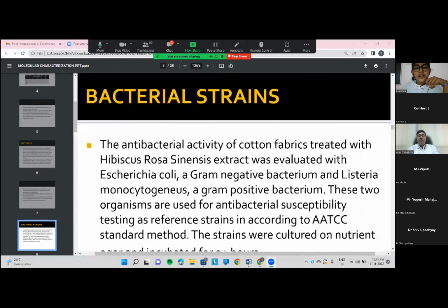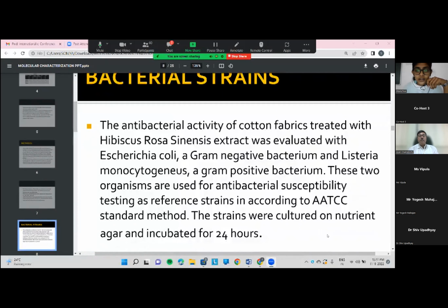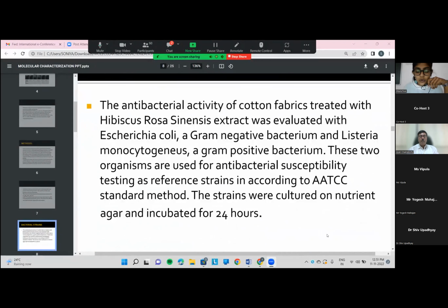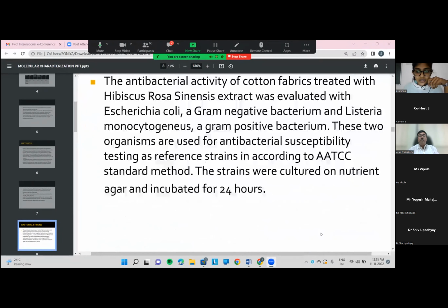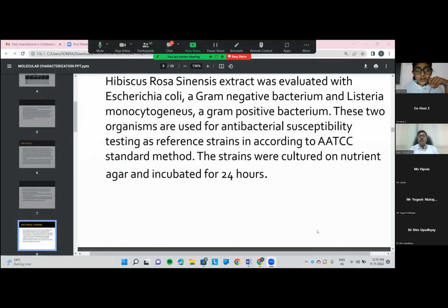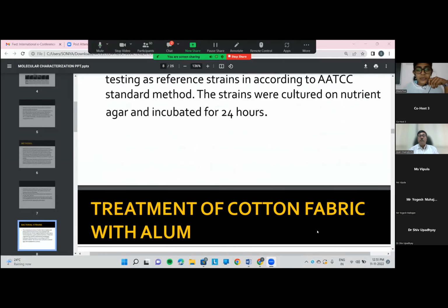Bacterial strains. The antibacterial activity of cotton fabrics treated with Hibiscus rosa-sinensis extract was evaluated with Escherichia coli, a gram-negative bacterium, and Listeria monocytogenes, a gram-positive bacterium. These two organisms are used for antibacterial susceptibility testing as reference strains according to the AATCC standard method. The strains were cultured on nutrient agar and incubated for 24 hours.